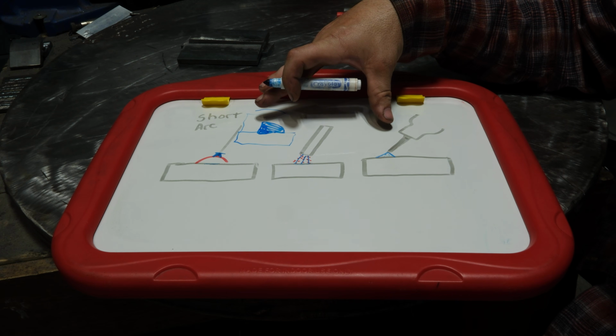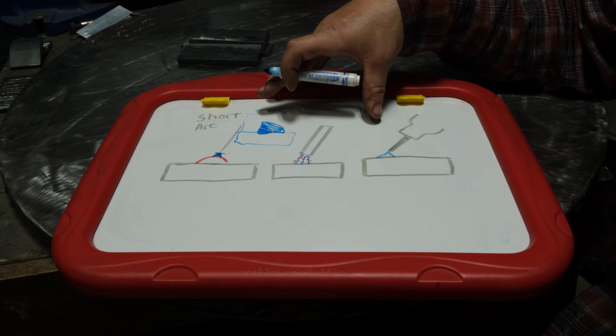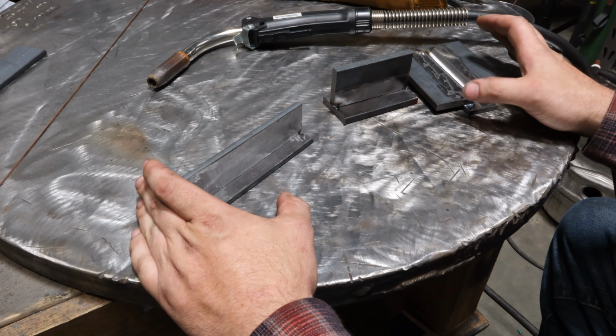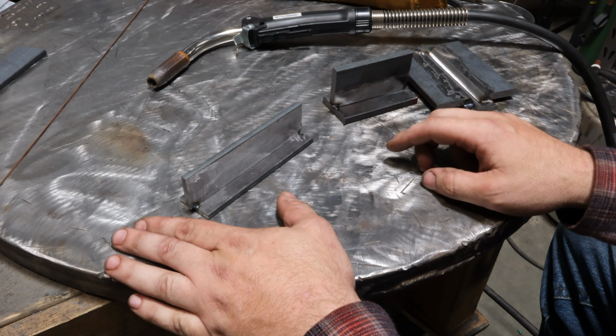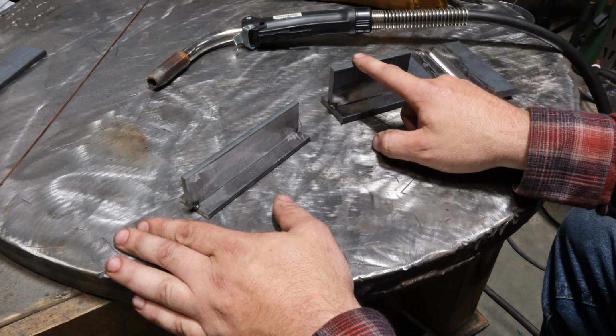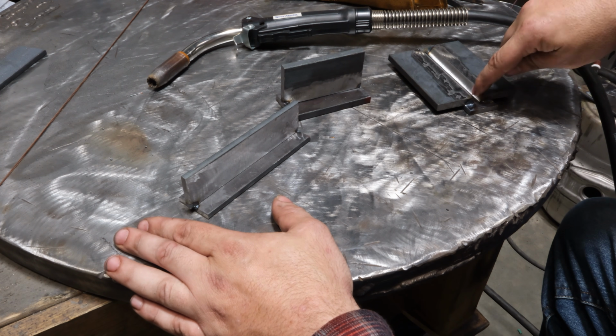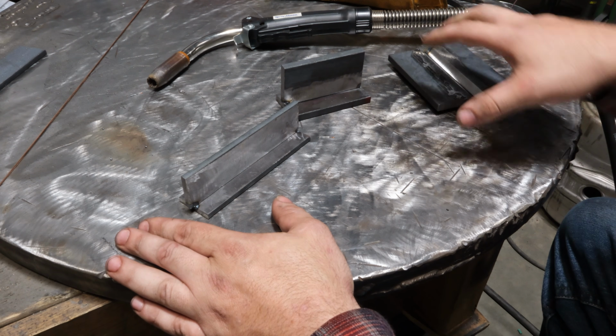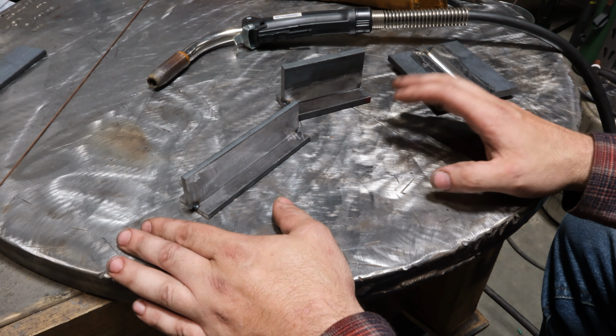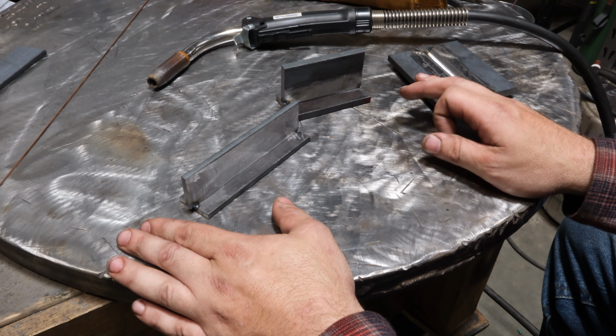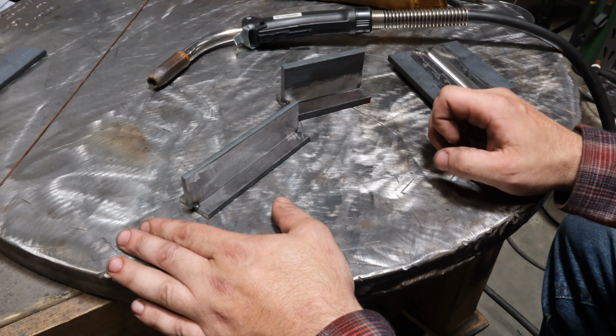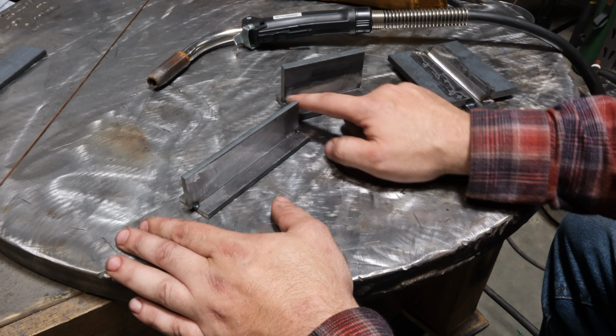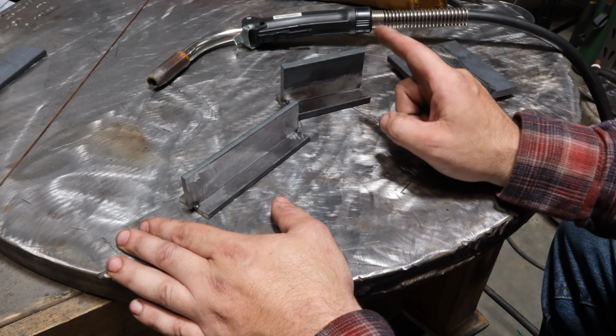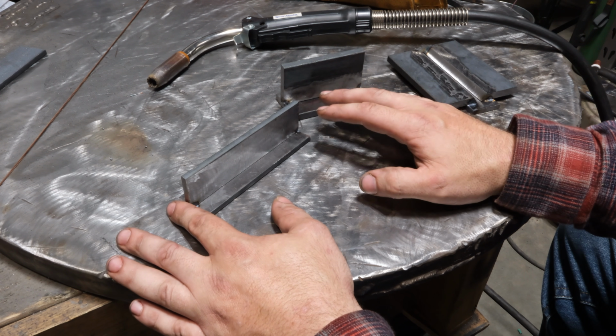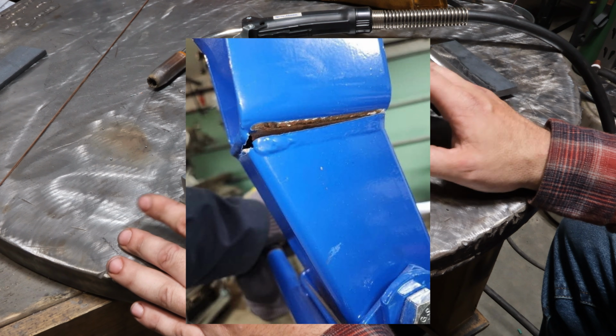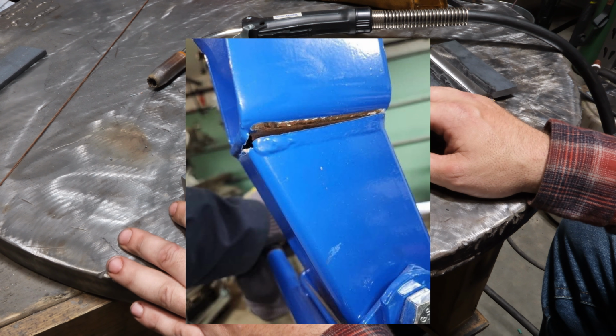Now that you understand more about this, let's look at the setup that I'm going to have for testing all of this so that we're all on the same page. So here are all of our test welds, and I may add another one, we'll see on that. We have 1/4 inch material here. This is 3/8 plate, both knife edge beveled and on a 1/4 inch backing strip. These are all prepped to bright, shiny, clean material, and that is a very important thing. If you're going to be doing short arc MIG on anything, even 1/4 inch and above, you need to surface prep your stuff. If you don't, and you have that mill scale, it's very common to get a lack of fusion because it doesn't penetrate very well through that scale, and that is part of why you see a lot of failed short arc MIG welds on thicker material, is due to poor prep. That will play a role.